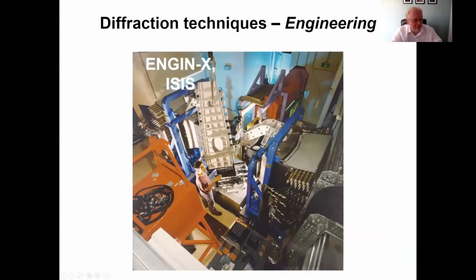And the other part of diffraction that we do is what we might call engineering diffraction, which is where we look at macroscopic things and we look at the bulk diffraction of these materials. What you can see in this picture here is actually part of the Airbus A380 wing, and we are going to do diffraction on the welds in that wing to determine if there's any local or residual stress produced by the welding process. And we can put the whole wing into the beamline.